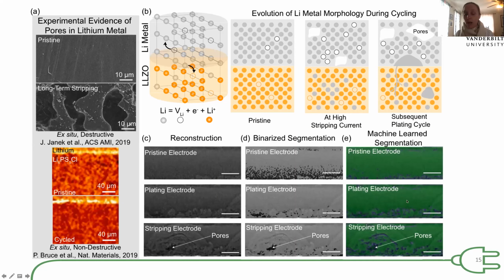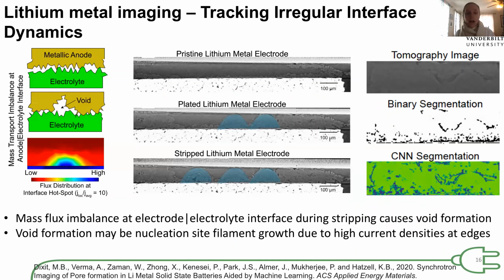But for those of you who are not X-ray tomographers, these are actually quite different. And I just want to draw your attention to here versus here. You can see that this binarized segmentation looks very different. And while one slice alone is not going to break the bank, when you're looking at thousands and thousands of images, this is very statistically relevant. Again, this is the tomography image. This is the segmentation we get using human in the loop or the open source binarization algorithms that exist.